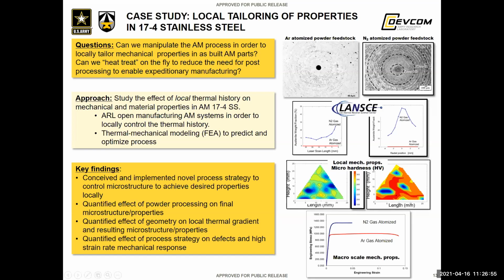As well as this one for this circular part, where instead of a regular back and forth hatch spacing, we had one that was basically concentric moving inward. From this, we found there's a critical position radially, where at the very center it had a very significant amount of austenite retained. And then we found that this retained austenite had a significant effect on the hardness of the object as well as on our mechanical properties.